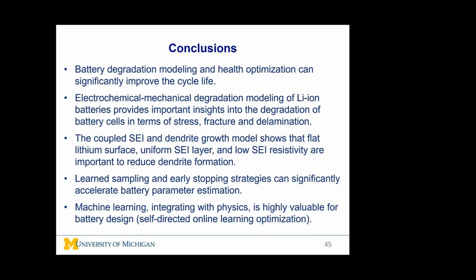So here's the conclusion. Battery degradation modeling and health optimization can significantly improve the cycle life. Electrochemical mechanical degradation modeling of lithium-ion batteries provides important insights into the degradation of battery cells in terms of stress, fracture, and delamination. The coupled SEI and dendrite growth models show that a flat lithium surface, uniform SEI layer, and low SEI resistivity are important to reduce dendrite formation. Learned sampling and early stopping strategies can significantly accelerate battery parameter estimation. Machine learning integrated with physics is highly valuable for battery design.